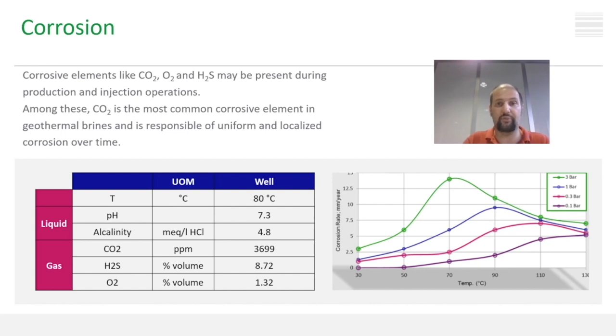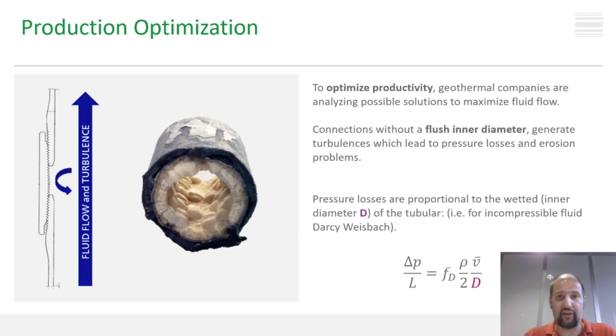Shall we also consider that these carbonates are brittle and can be easily removed, exposing the casing surface, leading to localized corrosion and pitting. Precipitation of carbonates and scales has another important effect for geothermal wells. Flow assurance is significantly impacted by ID restrictions. The scale deposits can be so severe as to close the production casing or impact the formation permeability.